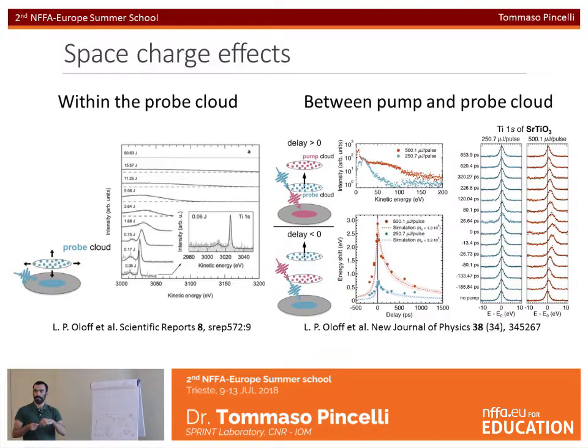But if we create multi-photon absorption, so we make the electron absorb several photons at once, then we can excite the electron out of the solid too, and create another disk of electronic charge at the surface of the system. So if we excite with too large photon densities, then we create a cloud from the pump and a cloud from the probe, and we have shifts that are changing as a function of the delay of the photoelectric spectrum.